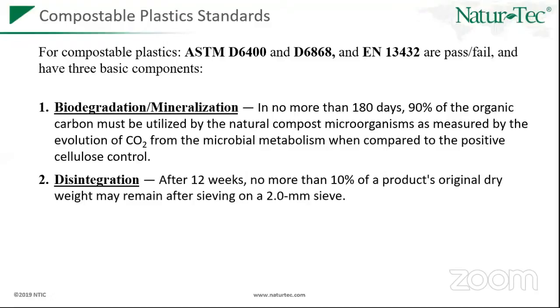The second point in the standard is disintegration, which means after 12 weeks, no more than 10% of the product's original dry weight should remain after sieving on a 2 millimeter sieve. The reason they put this is, let us say you take something like an aluminum foil. Now an aluminum foil contains no carbon, which means you will meet the mineralization methodology, because this first step is only for the carbon content in the material.